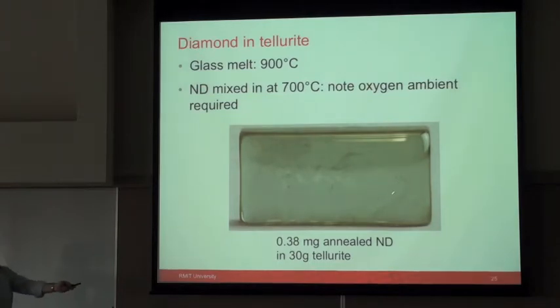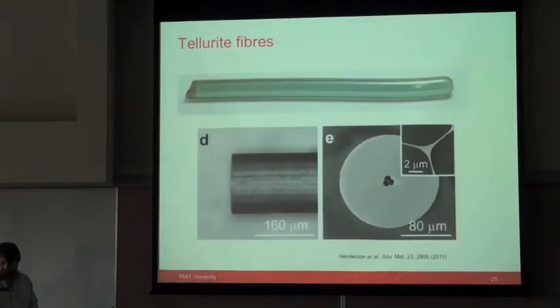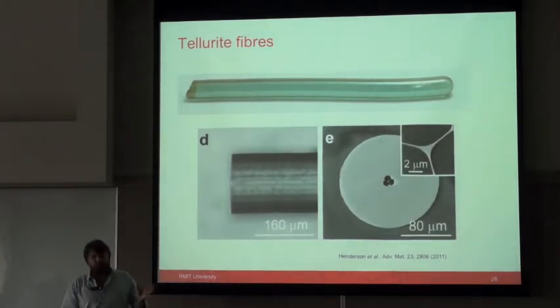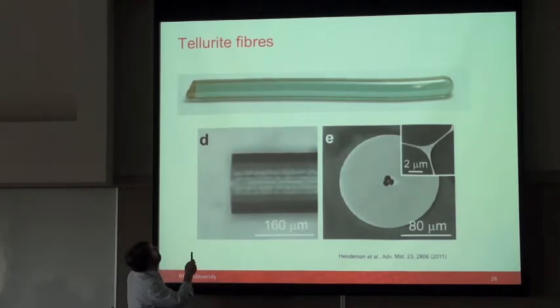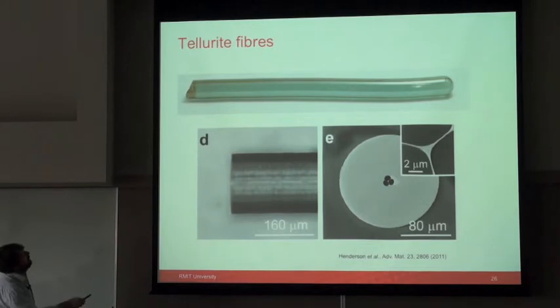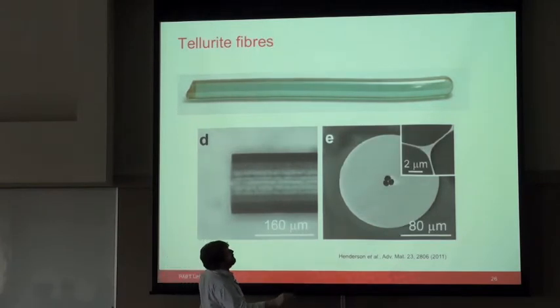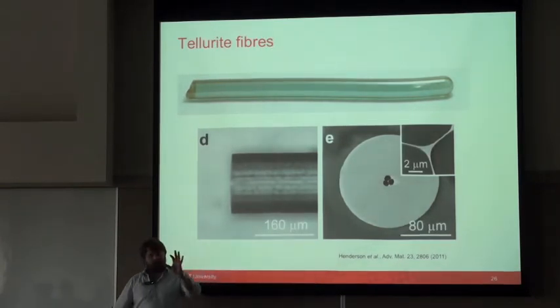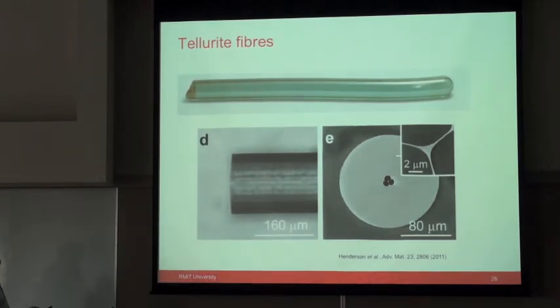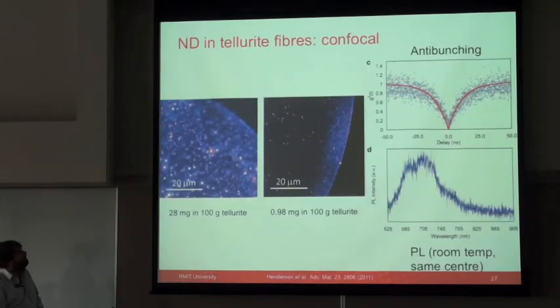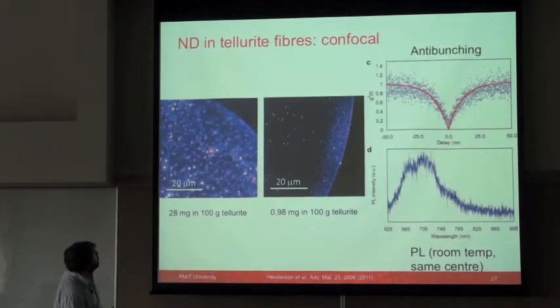Again, we continued to refine. This is another example of 0.38 milligrams of now pre-annealed nanodiamond in 30 grams of tellurite. Once you have this, you can leverage existing technologies, existing processes. This is a preformed optical fibre containing nanodiamonds. This is now an SEM of this, and this is our first attempt to build a microstructured optical fibre. This is done from a continuous piece of tellurite, so there are nanodiamonds all the way through this, and in fact this wasn't a very good sample. This sample here, though, I think really shows the proof of concept.